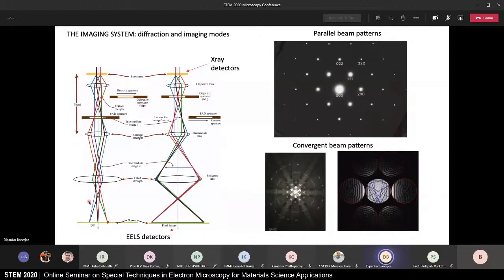And then you see an example of diffraction patterns that we get when we pick up the diffraction plane in the system. If you have a system of parallel beams, then you have the diffraction pattern that you see on top. If you have a convergent beam, then you have a different kind of diffraction pattern that's called a convergent beam diffraction pattern. And in a combination of these two, at the spatial resolution that the TEM offers, you can derive point groups, space groups, and so on.